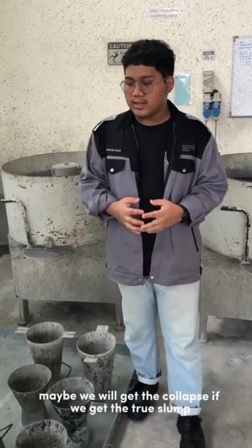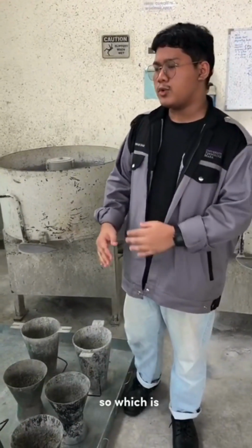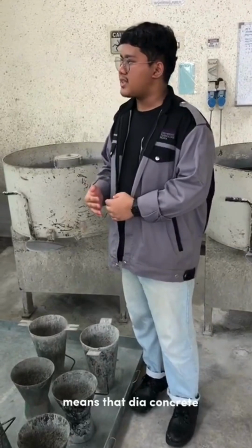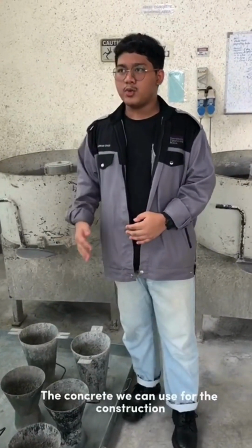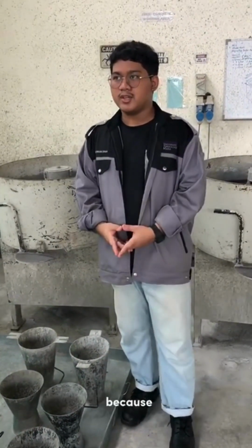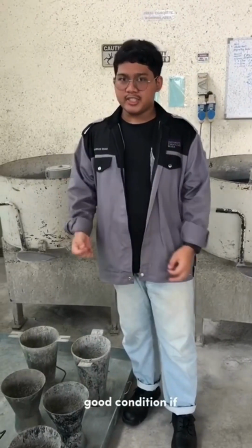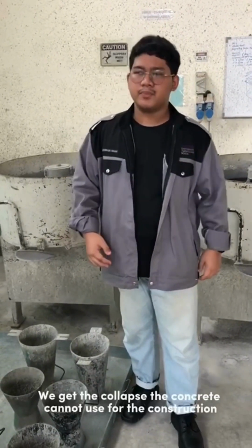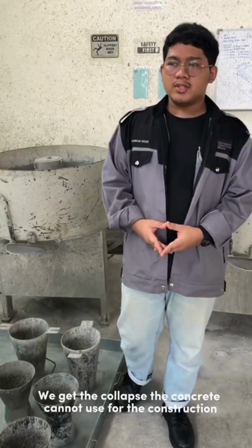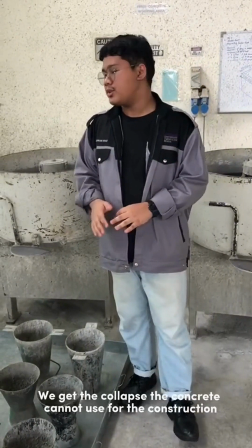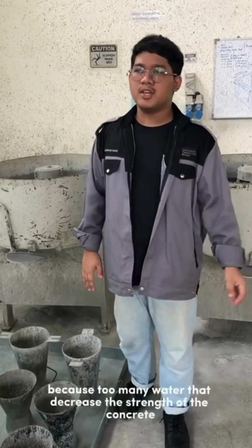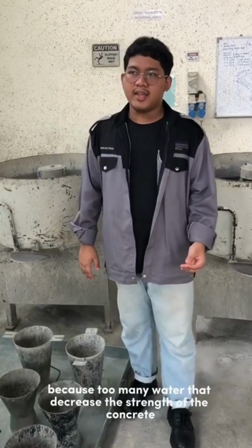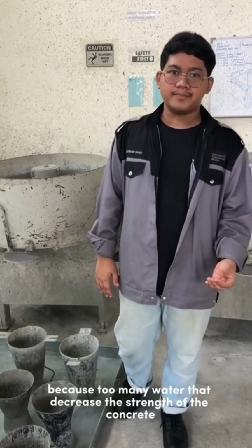If we get the true slump, it means that the concrete is in good condition and we can use it for construction. If we get the collapse, we cannot use the concrete in construction because there is too much water, which decreases the strength of the concrete.